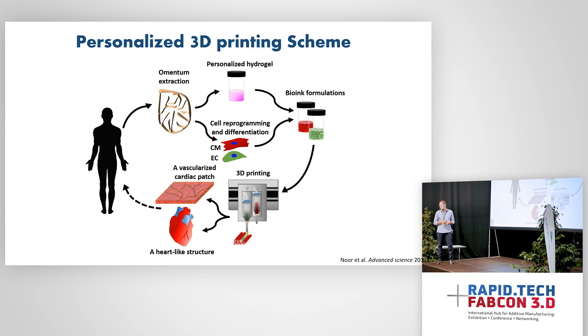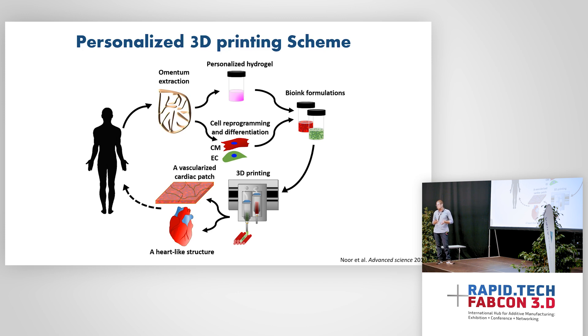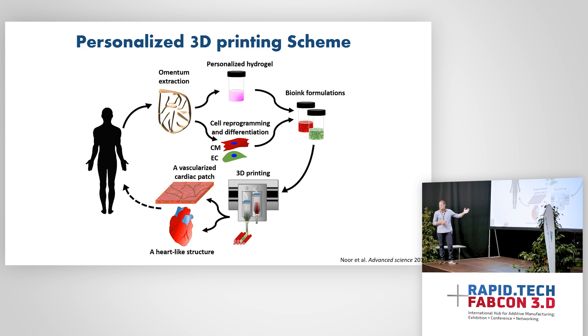How do we do that? We take a small fatty tissue biopsy — a very simple procedure done today in the hospital. Using this tissue, we separate the cellular and acellular material. While the cells are being genetically reprogrammed to become heart cells and blood vessel forming cells, the acellular material is processed into a hydrogel. We then mix the two together to form two distinct bioinks: one to form the heart patch, and the other to form the blood vessels. We then feed them into an extrusion bioprinter to print these tissues. Since these tissues originate from the patient itself, they will not evoke an adverse immune response after transplantation.